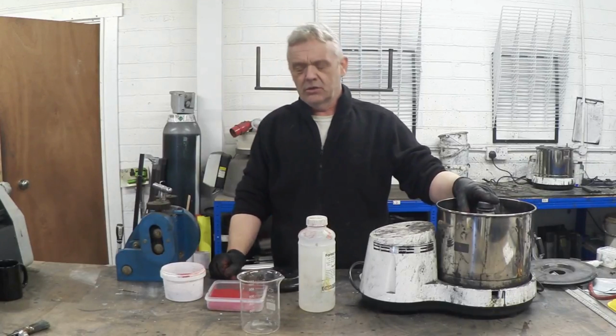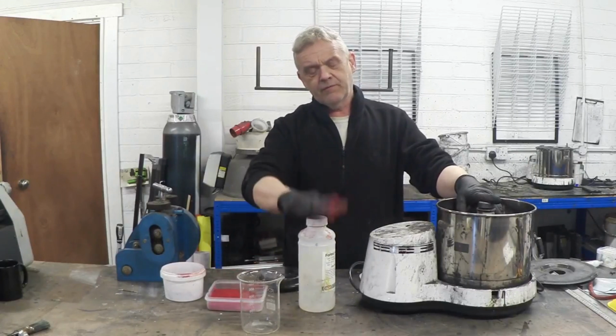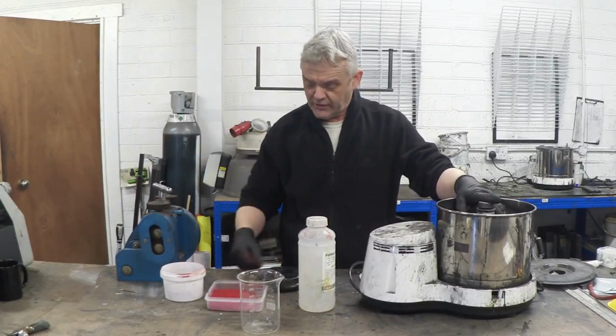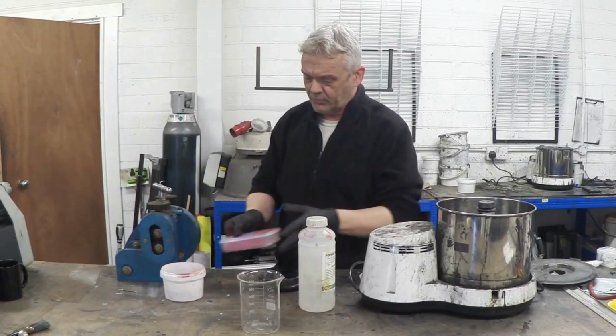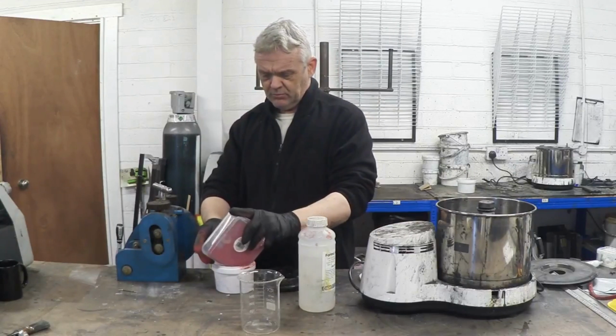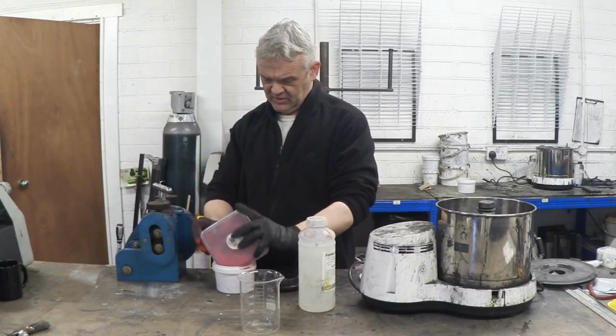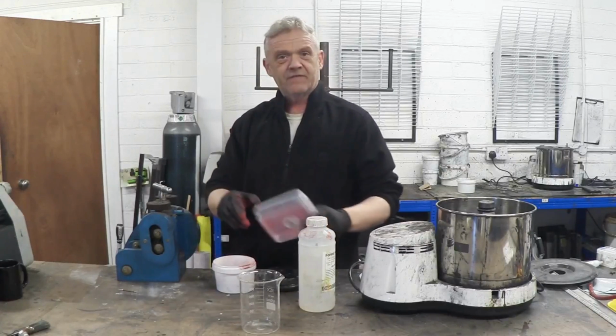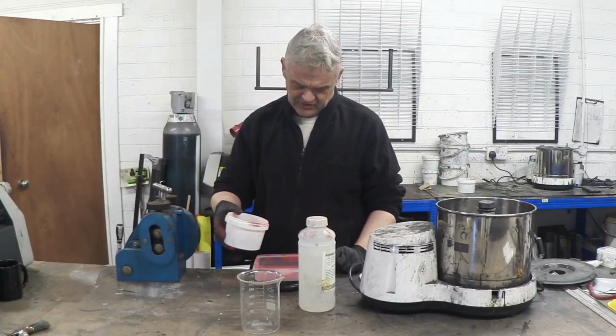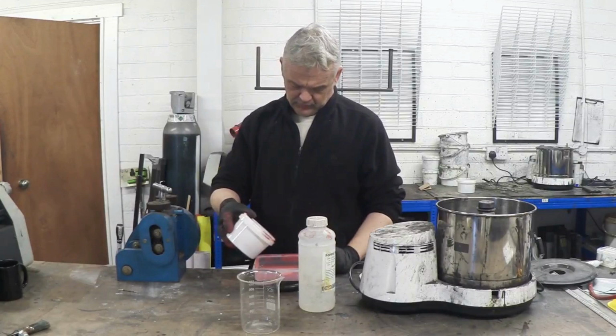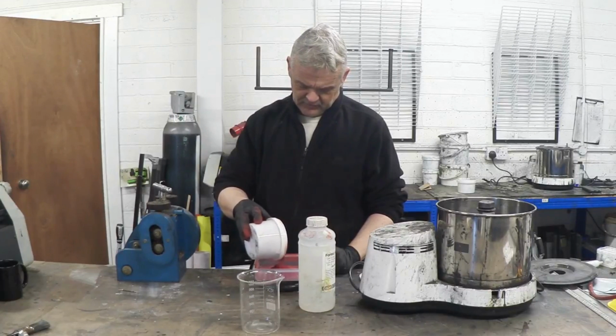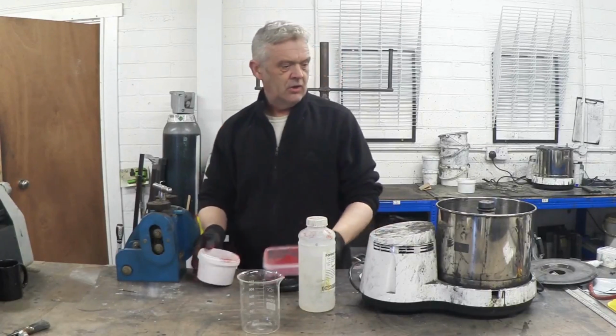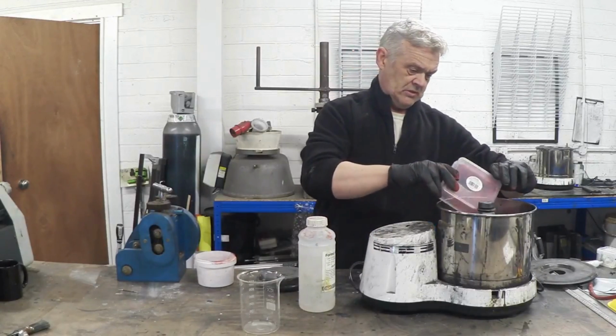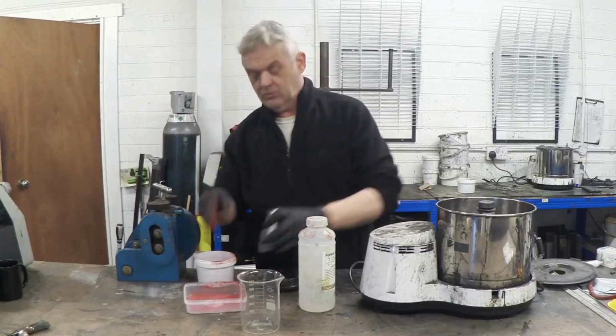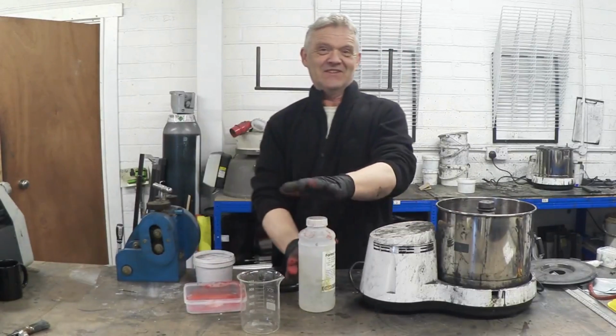Now, the ratios are 4:1. You need 1 part of your copper oxide and 4 parts of your formic acid. And in this case, we're going to use 125 grams of the red copper oxide, which I've got to put back in so that I can weigh this tray, and 500 millilitres of your 85% formic acid. So 125 grams of this stuff, there we go, and you just put it in. And when we've added the acid, you turn it on. And then 500 millilitres of this stuff.